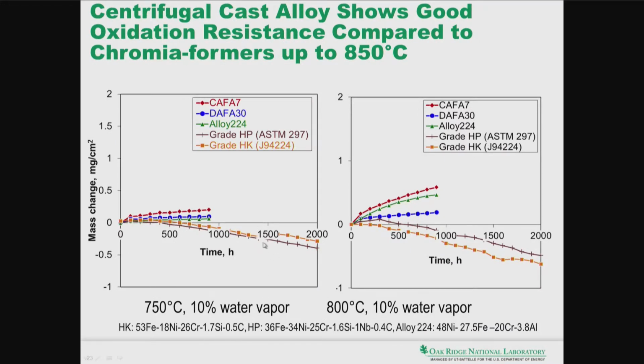So the first set of data you see here is the oxidation resistance as a function of temperature in the 10% water vapor air environment. What we compare here is the mass change, and there are several alloys here, so let me walk you through them. The CAFA 7 and DAFA 30 are alumina-formers, and alloy 224 is a high nickel alumina-forming alloy. And as you can tell, these alloys keep a very low mass change as a function of time when compared to the HK and HP alloys, which have shown significant loss in mass, which is related to the spalling.